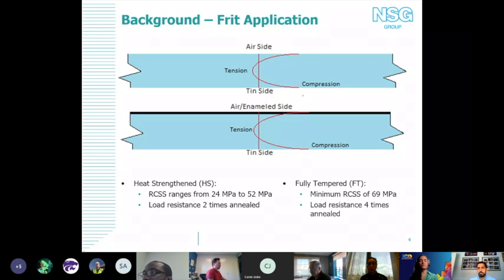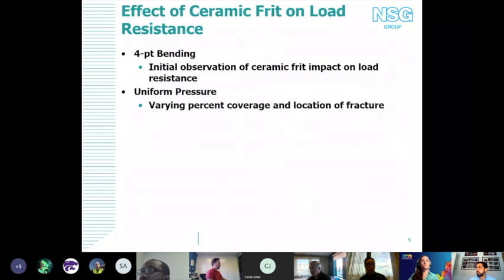So whenever you go through and you add that ceramic frit, you see within the glass you actually have an asymmetric surface stress at the glass surface, at least, because theoretically your maximum residual compressive surface stress should be occurring on the surface of the enamel. And so when you go through, you design heat strengthened, theoretically has a load resistance of 2 times annealed glass, and fully tempered should have a load resistance 4 times annealed glass. So this is just a general background on where we're starting. If you move forward, Kate.